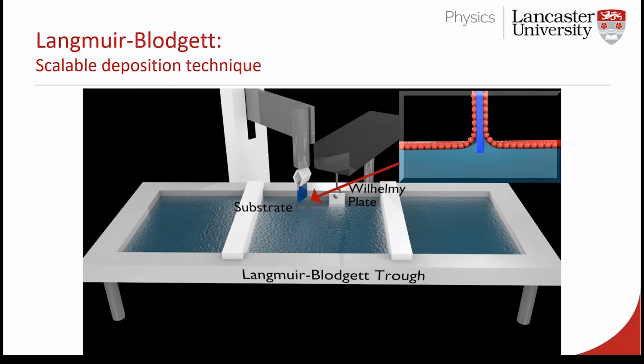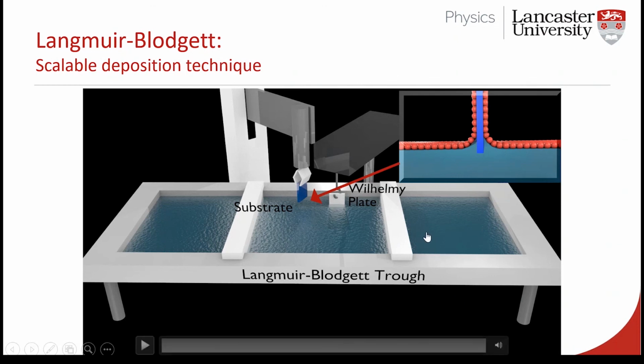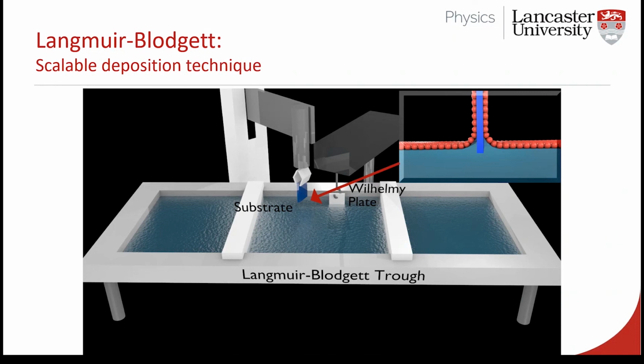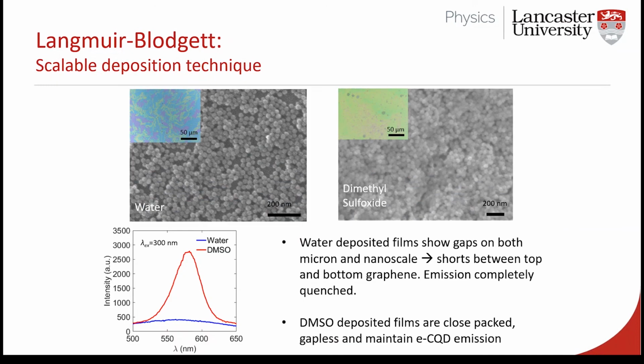Once I've got that densely packed film on the surface, I pull my substrate. You saw this blue substrate go through the water. I pull that out and I keep squeezing the film, and I push my film of interest onto the surface. And we can do this in many different ways. So here you've seen a single example where it's deposited on both sides. We can easily deposit on a single side. We can deposit multiple layers. We have multi-compartment troughs where we can deposit different materials systematically. It allows us to produce very densely packed, large area films and material.